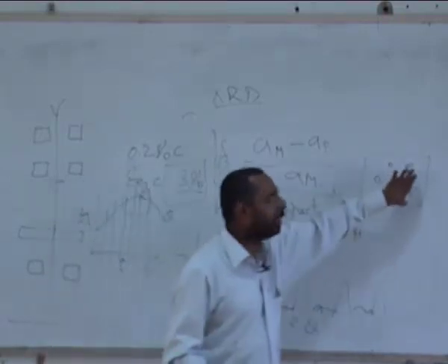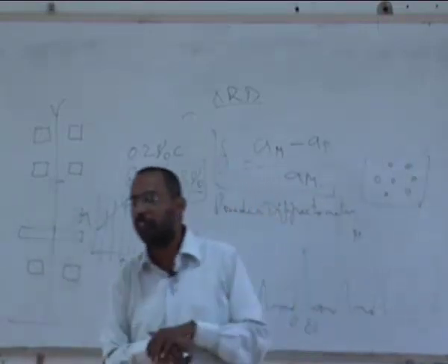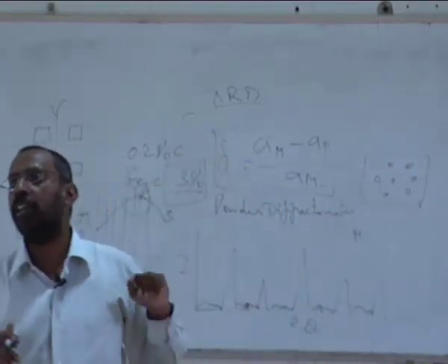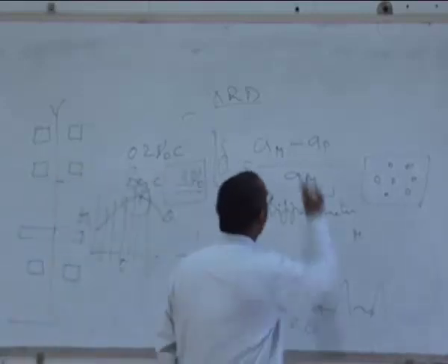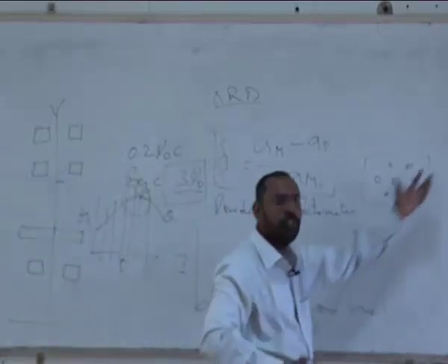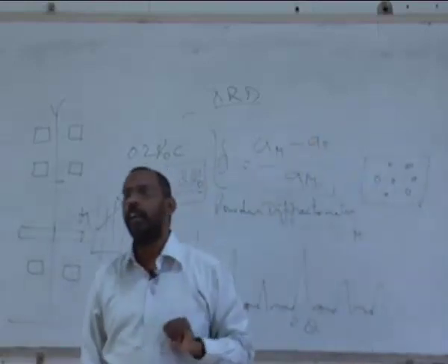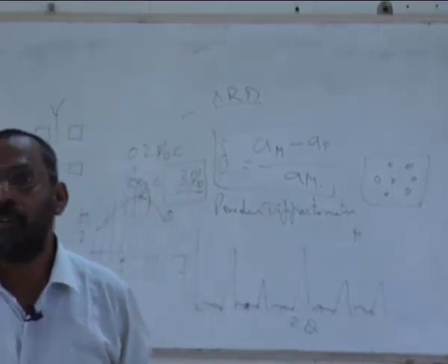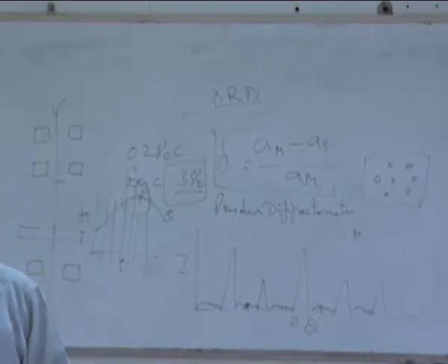So as a result, in the beginning of the transformation, you may have only 0.5% or 1% of these precipitates which have just formed, and they have not yet completely grown to the size and volume fraction that they will have. So at that stage, if I use an XRD, I may not be able to see any of this. My XRD pattern may not show any epsilon carbide at all. So this kind of thing can be found out if I use a TEM. We will see how to see them in the TEM in the